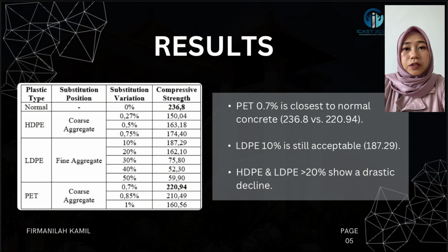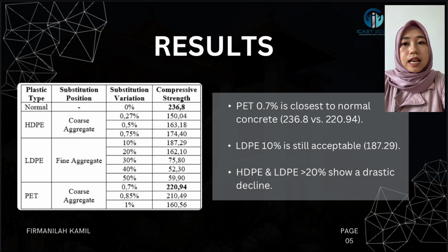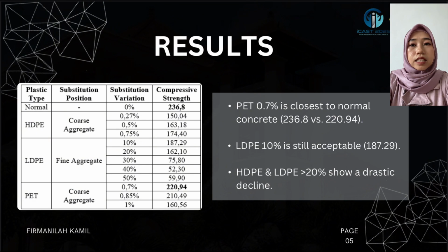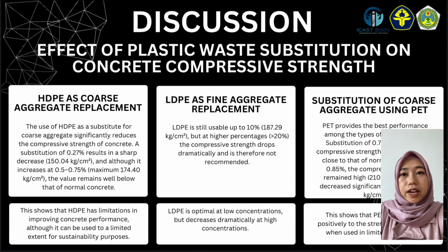LDPE at 10% substitution still produced acceptable strength values, reaching 187.29 kg per square centimeter. However, when the substitution level of HDPE and LDPE exceeded 20%, the compressive strength experienced a drastic drop, indicating significant negative impact on mechanical performance. This result suggests that while certain levels of plastic substitution can be tolerated, excessive amounts significantly reduce the quality of concrete.